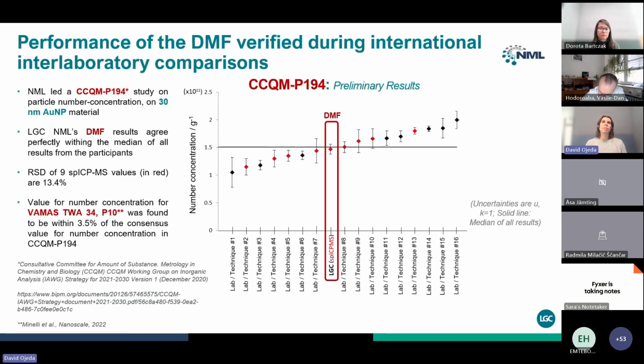Also, the performance of the DMF was verified through international comparisons at the CCQM level. In this specific CCQM study, the sample of interest was the 30 nanometer gold nanomaterial, and as we can see on the graph, the results obtained by the DMF were completely in agreement with the consensus value for the CCQM study.